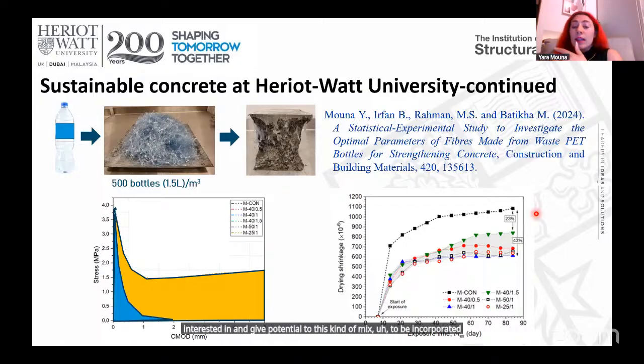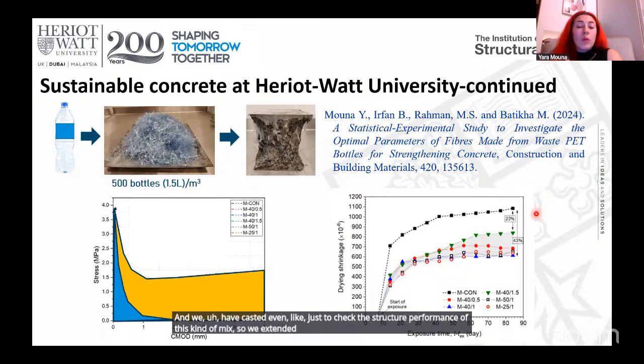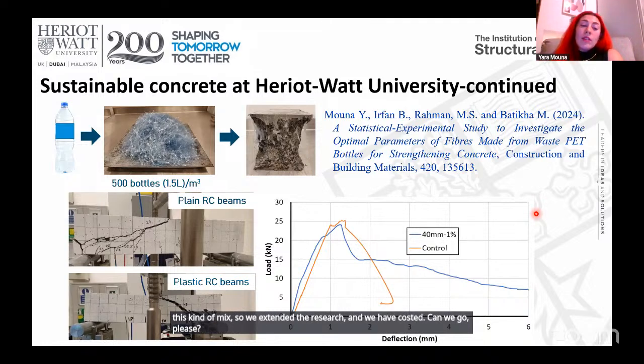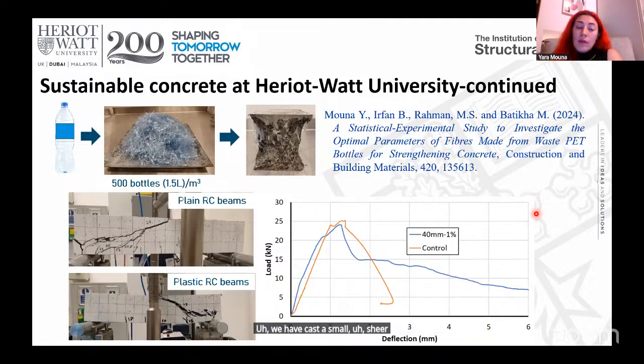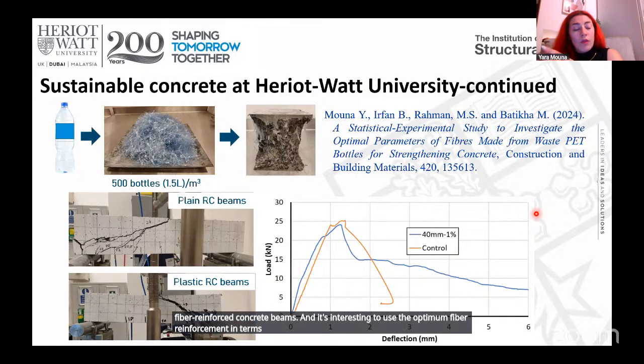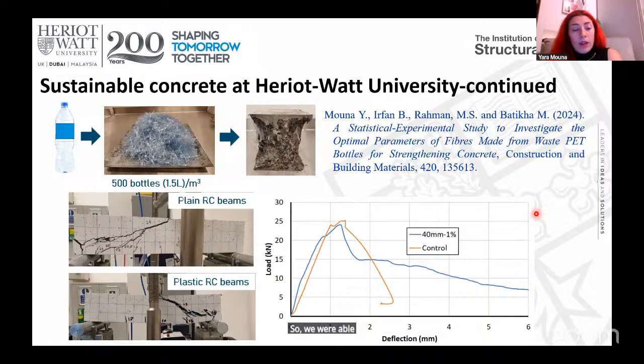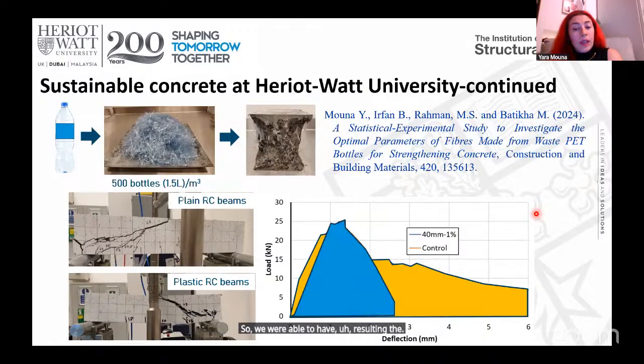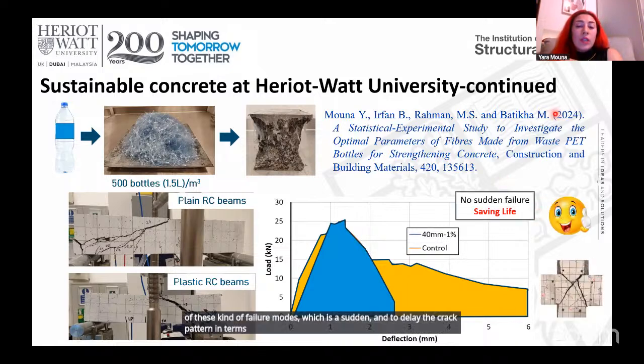So we extended the research, and we casted small shear-critical PET fiber reinforced concrete beams, just to check the structural performance of this kind of mix. It's interesting to use the optimum fiber reinforcement in terms of geometry and volume fraction. So we were able to reduce the brittleness of these kinds of failure modes, which are sudden, and to delay the crack pattern, decreasing the sudden failure.